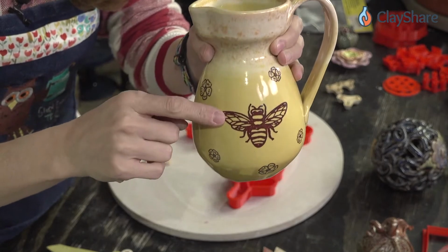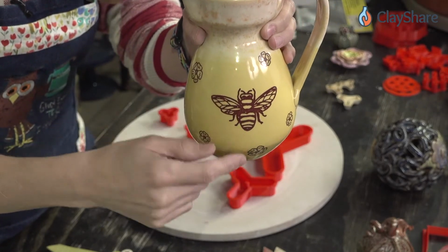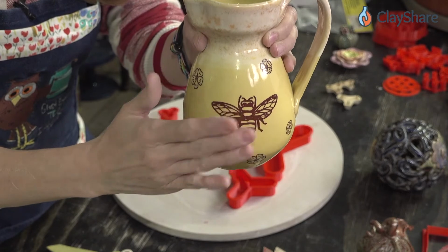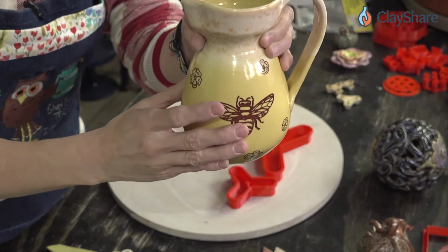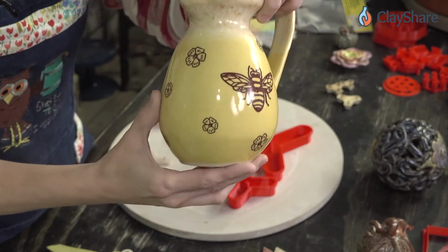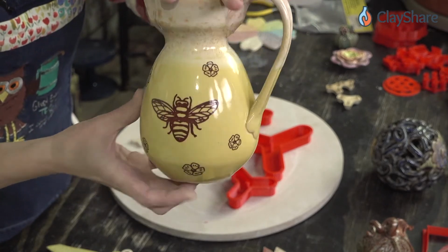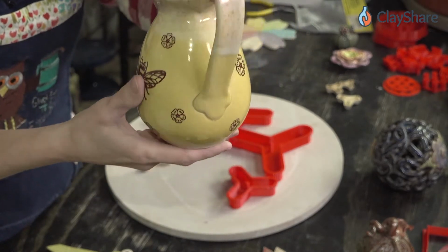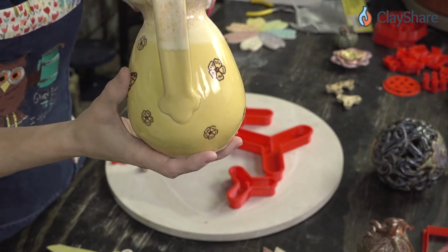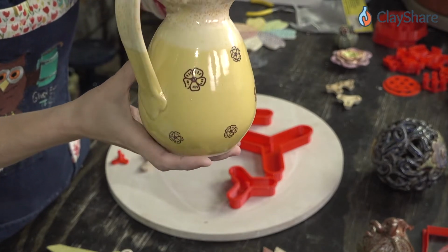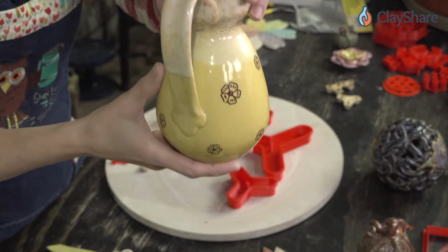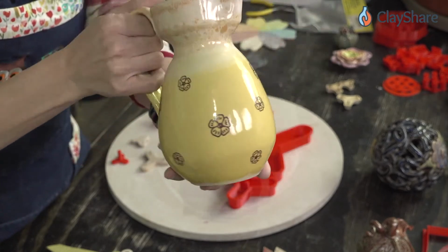And then I put a decal of a bee that I drew, and I printed it out and applied it. We did this a few weeks ago in a tutorial. We did this together. And then I fired it again to cone 5. And you can see the glaze, we've got no shift in color. We've got no change in surface quality. It's just as glossy and shiny as it was when it came out of the glaze firing the first time.